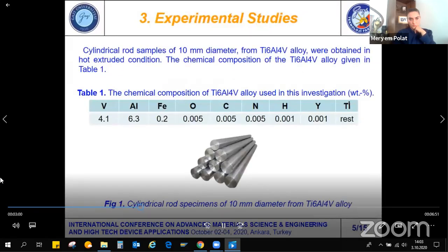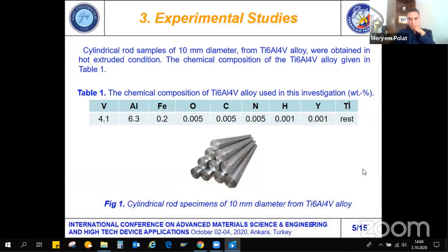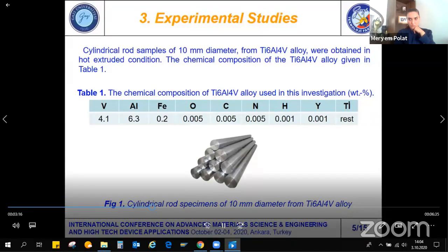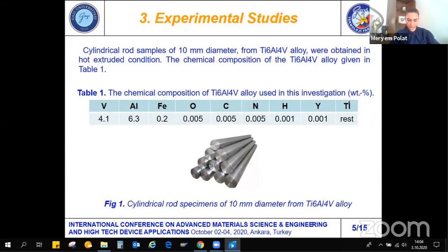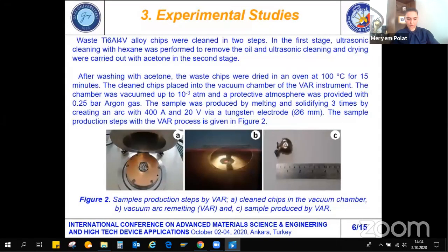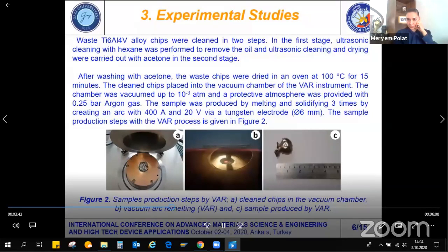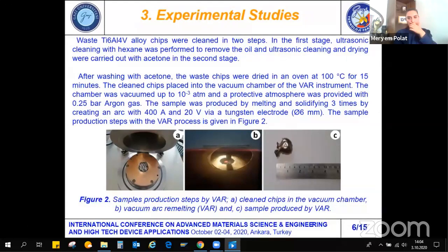The cylindrical rod samples of 10 mm diameter of titanium 6 aluminum 4 vanadium alloy were obtained in hot extruded conditions. The chemical composition of the alloy is given in table 1. The waste chips were obtained from a lathe machine located in Ankara. Waste titanium 6 aluminum 4 vanadium alloy chips were cleaned in 2 steps. In the first stage, ultrasonic cleaning with hexane was performed to remove the oil, and ultrasonic cleaning and drying were carried out with acetone in the second stage. After washing with acetone, the waste chips were dried in an oven at 100 Celsius for 15 minutes.